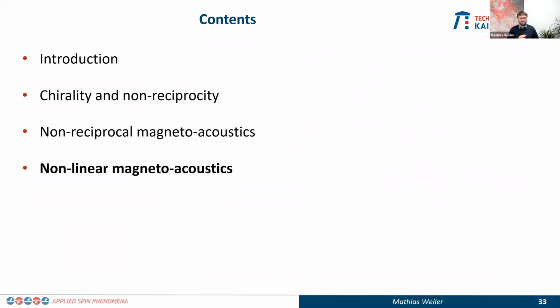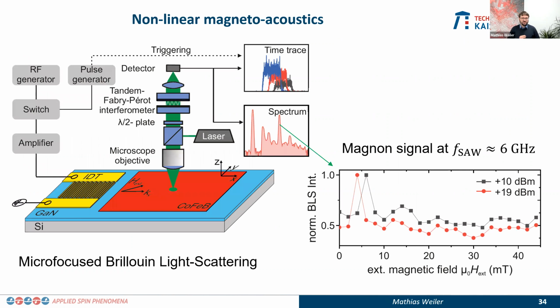Now I'll take the remaining 2 minutes to very briefly touch on nonlinear effects. Nonlinear effects are a very important topic in the field of magnonics. Magnonics really thrives from nonlinear interactions between magnons. And we question ourselves, can we actually use surface acoustic waves with sufficiently high amplitude to drive nonlinear effects in, for instance, a thin film of cobalt iron boron, which has a damping that is typically so high that it will be very challenging to use a microwave antenna to excite nonlinear spin waves in this material.